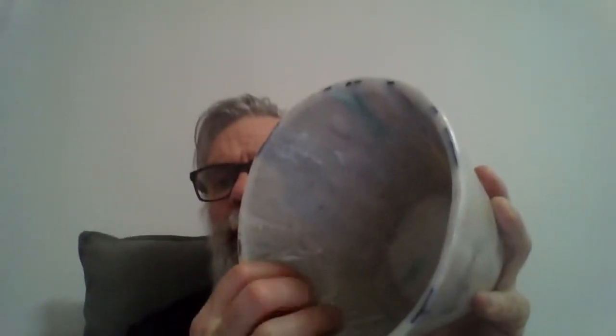As you can see in the bottom image on the version 2 bowl mold, the hexagon one, there we had enough material when we squashed it, so it came out the top of it and goes over the top, so we get a good finish. So when you get the temperature right, this was our latest version that we've tried. If you get the temperature right on the bowl, you get the right amount of material into it and you press it, you get a fairly good finish without much cleaning up, and it comes out as a finished product. There's little things that you finish off then, so you might clean edges off and tidy them up or something like that. But that's what we found.